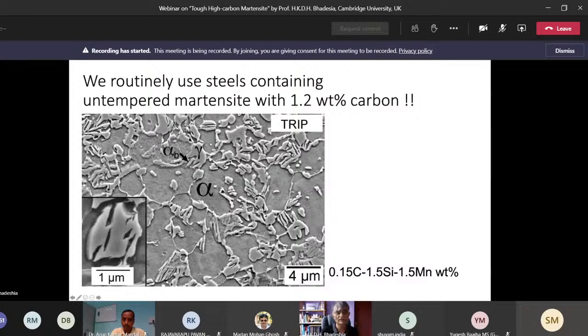And it has a mixed microstructure. This is ferrite here, which is very soft. And this is a mixture of austenite and bainite. The carbon concentration of this austenite is 1.2 weight %, even though your average alloy concentration is 0.15. And that's because when the ferritic phases form, the ferrite and the bainite, they partition the carbon into the austenite. So even though you have a low average carbon concentration, the carbon in there is 1.2 weight %. And when you actually put this into production, the forming operations and so on, this austenite will partly decompose into martensite under the influence of the stresses and strains. And that martensite is untempered with 1.2 weight % carbon, and yet we are not bothered about this.